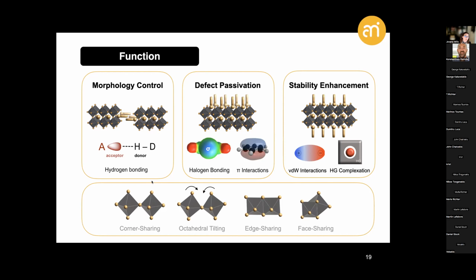overlaps. Furthermore, using other, perhaps to an extent unconventional, non-covalent interactions in this regard, such as halogen bonding or even pi-based interactions, to not only control morphologies, but also suppress specific defects, or furthermore, building self-assembled molecular layers that are highly hydrophobic based on, for instance, van der Waals interactions to increase the resilience against moisture, or suppress some of the ion migrations, where, for instance, host-guest complexation strategies are further advantageous.